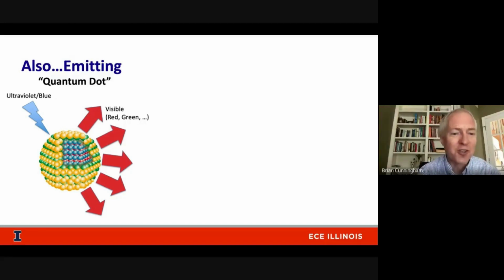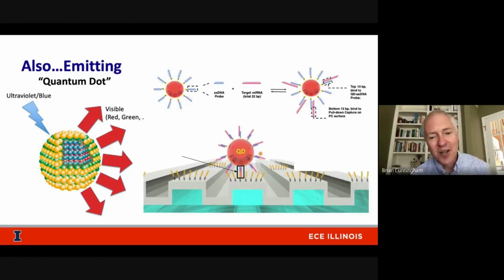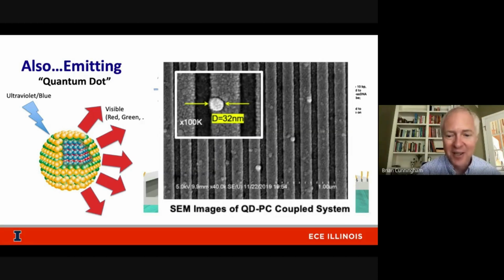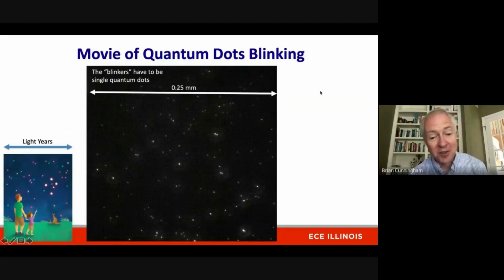We can also use a photonic crystal to excite photon emitters, such as quantum dots. When we design a photonic crystal that has a resonance in the ultraviolet part of the spectrum that excites quantum dots, we've also done some assays for microRNA using quantum dots as labels. Not the same as the toehold probe method that I mentioned before, but also very selective, where individual quantum dots on the photonic crystal surface can be clearly observed through their enhanced excitation provided by the photonic crystal.